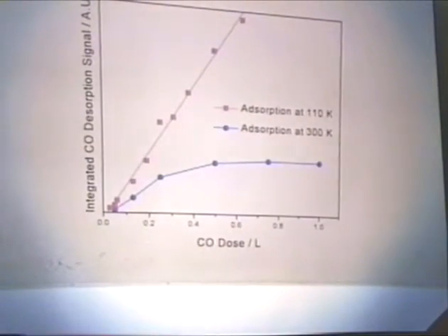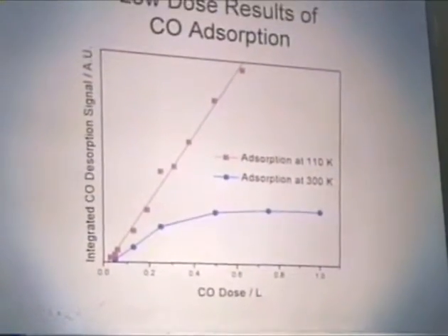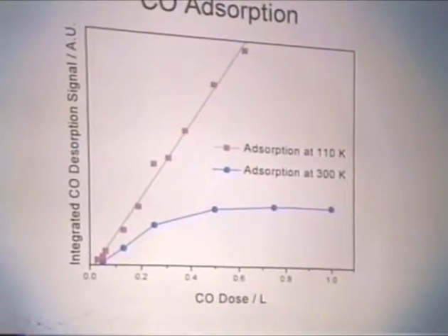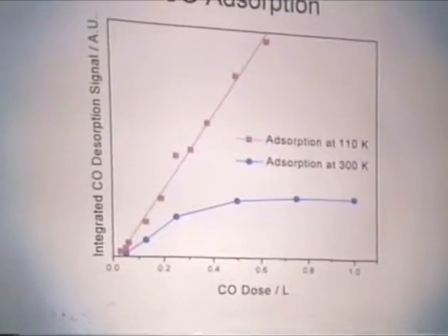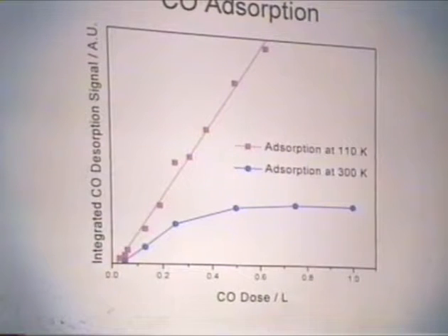So if we expand the scale and look across the low dose range and examine the slope of this line, the slope is proportional to the sticking coefficient, which is the ratio of the rate of adsorption over the total rate of collisions with the surface. And the sticking coefficient for the adsorption at 110 Kelvin, you can see, is very linear, indicating a constant sticking coefficient across this dose range, which indicates precursor-mediated adsorption.